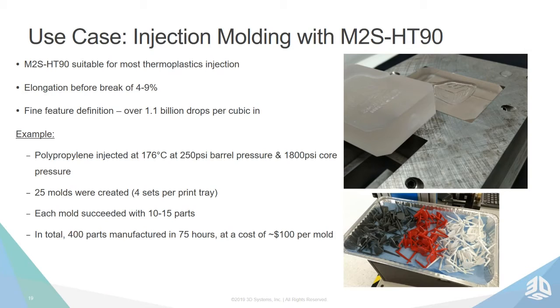In this nice example in the photographs, we have polypropylene parts. They were injected at 176 degrees C at 250 psi barrel pressure and 1,800 psi core pressure. 25 molds were actually created. That's 4 sets of parts per print tray. Each mold succeeded with roughly 10 to 15 injected parts. So in total, 400 parts were manufactured in just 75 hours at a cost of around $100 per mold set. So that's a significant time and cost advantage compared to the traditional method that could take weeks for the metal tooling to arrive, and which would typically cost thousands to create those metal tools themselves.